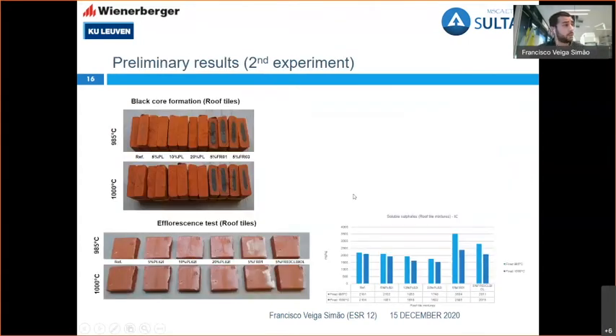And on the preliminary results, you can see that indeed with Plombières, even if you increase to 20%, there is no black core formation. It means a good, already clean material, even though in the efflorescence test you can see some efflorescence stains coming up. And on the Freiberg material, as you see, the non-clean and the clean, there is a decrease in the black core zoning. But this also shows that on the efflorescence you have some different results. So there is more efflorescence on the non-cleaned than on the clean one, which is expected to have less sulfate content. As shown here, the soluble sulfate content decreases indeed on the clean one. Nevertheless, it is still high to integrate into the ceramic mixtures.